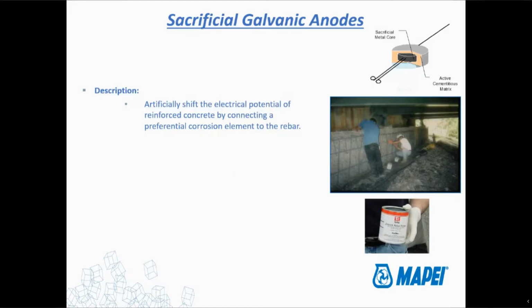So we do have the technology to do that. They're called sacrificial galvanic anodes. They're generally a sacrificial metal core of some kind, generally zinc, that are encased in a cementitious matrix of some sort. They're all manufacturer specific, so they all have their own special sauce in them. They're supposed to do different things. But the idea is by putting a piece of zinc and attaching it to the metal, the iron, zinc is going to preferentially corrode in the presence of iron. So all the corrosion, instead of happening around the patch like it was before, is going to happen in that zinc anode.